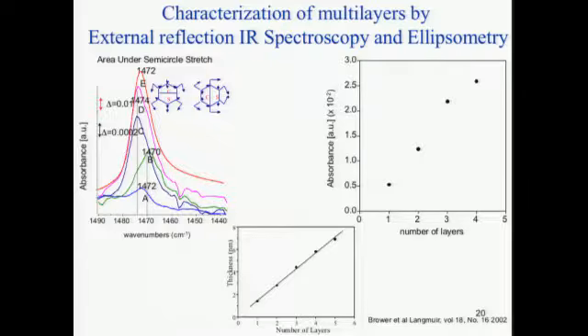Here I'm showing some grazing angle FTIR data, which, as I mentioned earlier, is very sensitive to the orientation of the molecule on the surface. And it tells us something about the degree of order. And so as you increase the number of layers, which is what I'm showing here, we actually made this in solution as well and looked at the Raman spectra of that. I'm not going to get into those details, but just keep in mind that the relative shift from this 1470 peak is giving us some idea about the order within the multi-layer system.